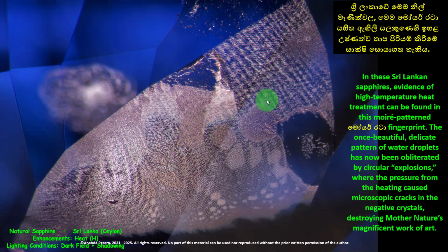The once beautiful, delicate pattern of water droplets, you can see here, water droplets, has now been obliterated by circular explosions, where the pressure from the heating caused microscopic cracks in the negative crystals.